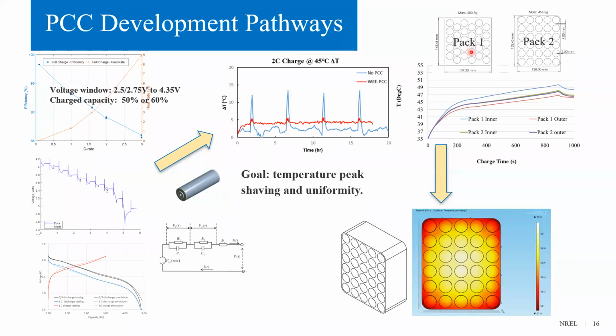Compared with Pack 1, the weight of the PCC housing case of Pack 2 is reduced by 10%, and the cell was relocated. Simulation results show that at 2C charged to 50% SOC, Pack 2 can maintain a minimum temperature difference among the cells, as can be seen from this figure.